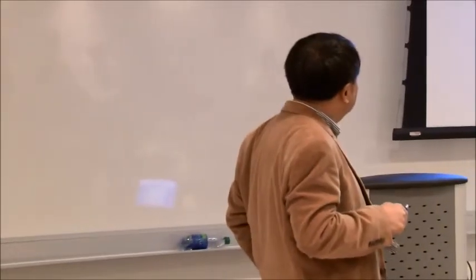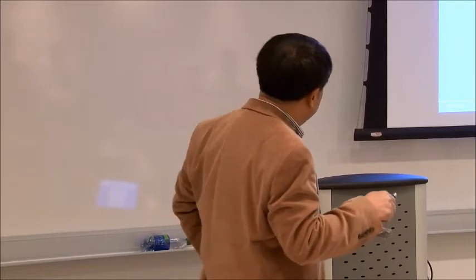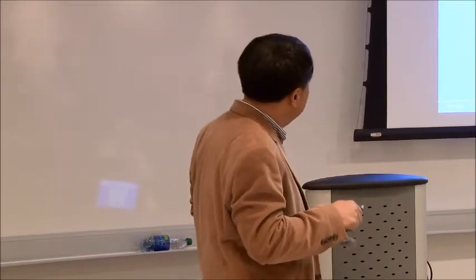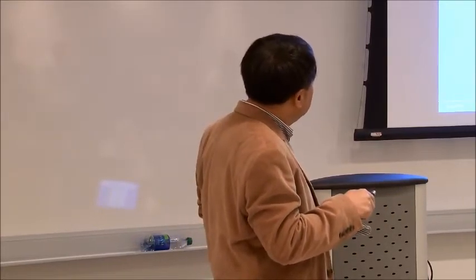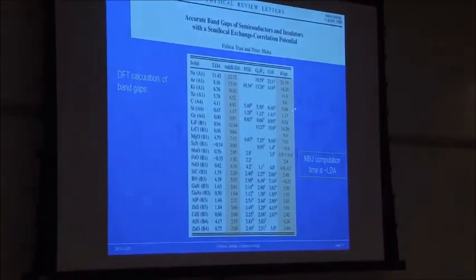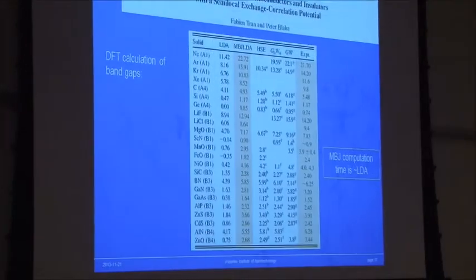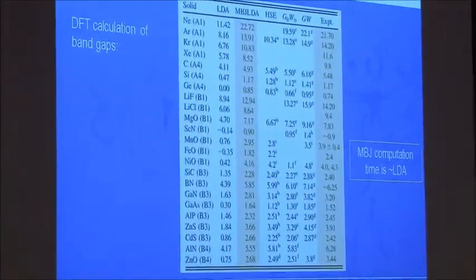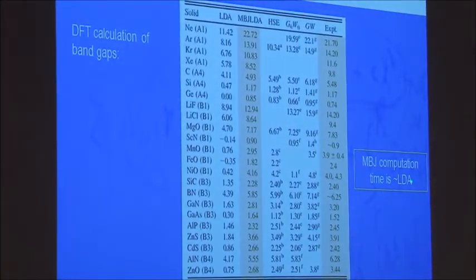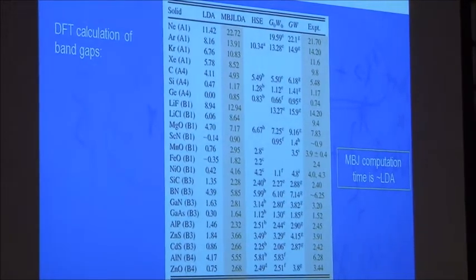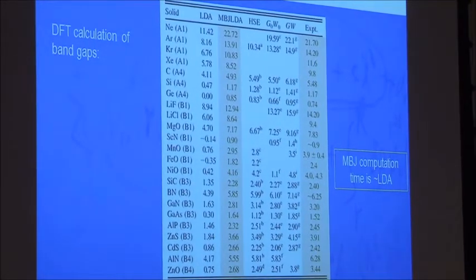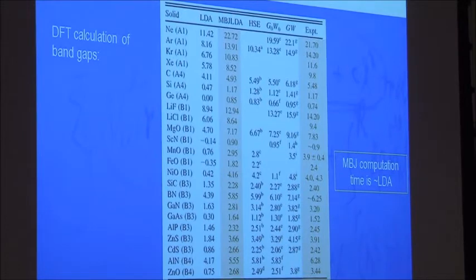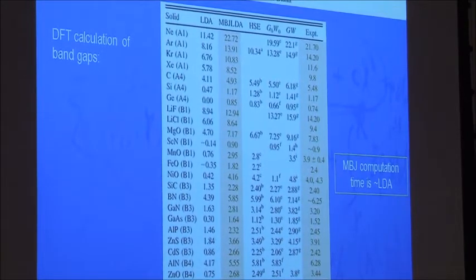BJ, okay, and actually both of them, Becke is in Canada, right? Quantum chemists, very well-known quantum chemists. They have some functional, and these people modified it, so this MBJ, okay. And what they found is that if you do that, somehow you can get very good gaps for many compounds. And the calculation speed is as fast as LDA. So this is very good. This is not a fundamental physics solution, but it's a practical solution to this band gap issue.